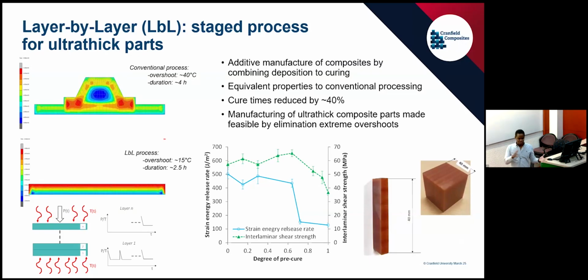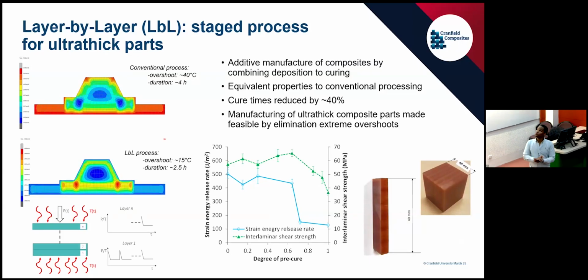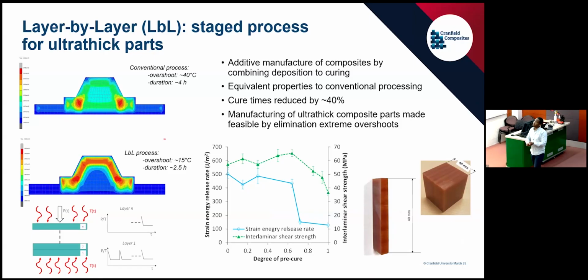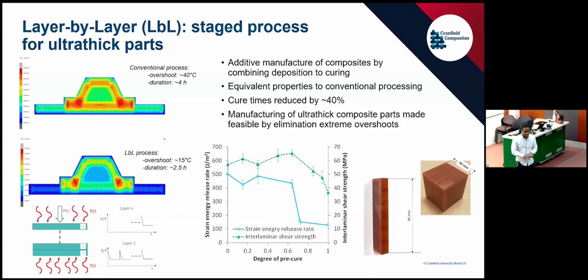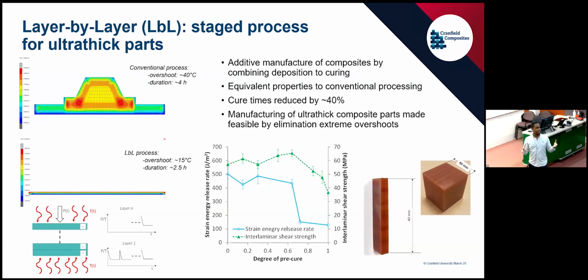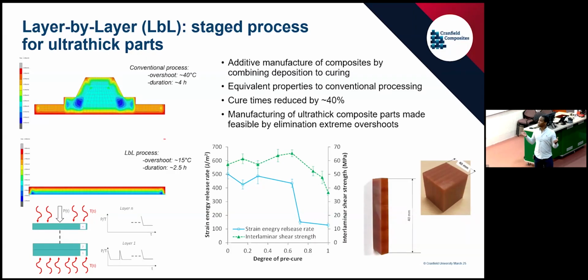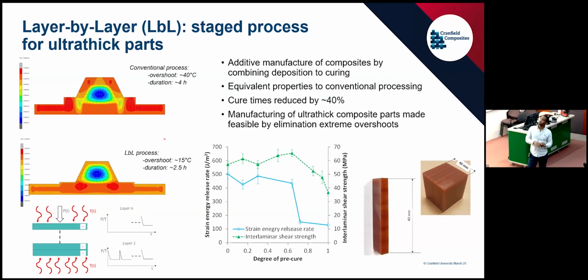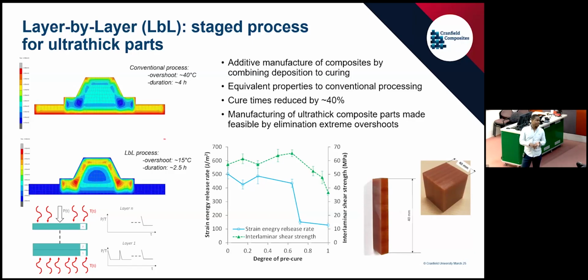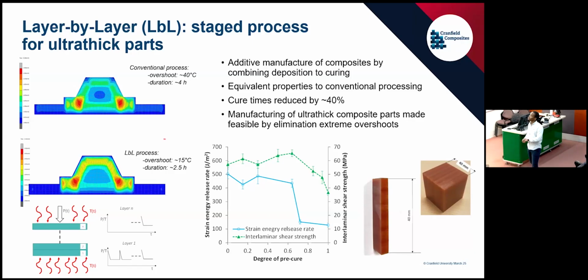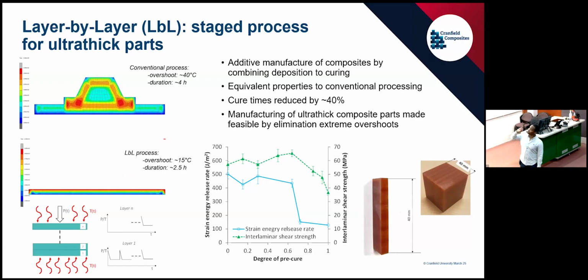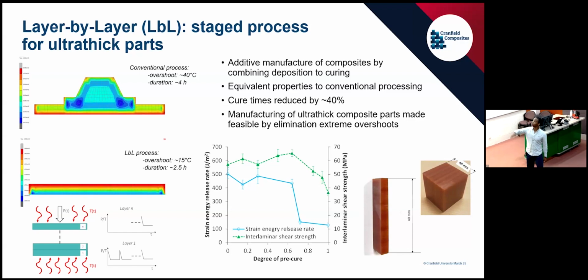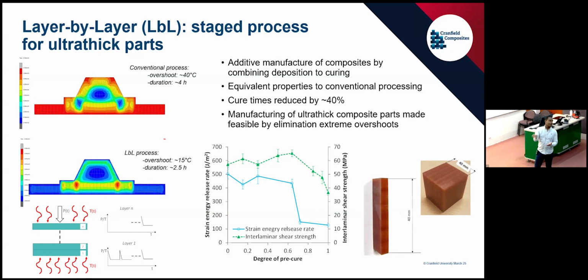Another really nice key area of research that we like to show off is this work on layer by layer curing of composites. The problem here being when you have really, really thick components in an autoclave and an oven, you typically have large temperature overshoots, which are inefficient and might cause damage to the material. So we have developed, within the center, Alex has developed this method of layer by layer curing of the material, where you can put a layer of the material down, cure it with laser or flash lamps, and then you come back and deposit another layer as well.